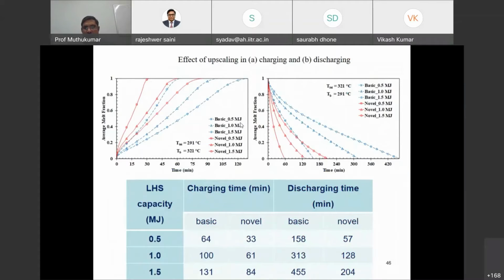These are the basic capsules like 0.5 megajoule, 1 megajoule, 1.5 megajoule. And here we have the novel capsules, again 0.5, 1 and this one. Now, if you see this one, the novel capsule having a high capacity of about 1.5 megajoules performs almost similar to the basic capsule of 0.5 megajoule. So that means even if you increase the size of the novel capsule by 3 times, its charging and discharging is almost similar to the basic capsule, which is 3 times smaller in dimension. That's what I'm trying to say. So in that way, you can reduce the size as well as the space requirement.